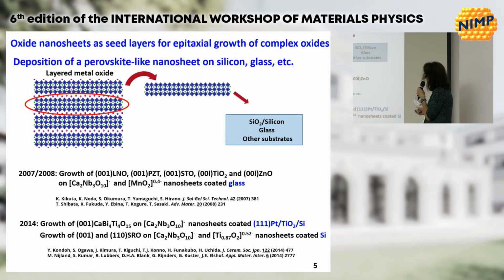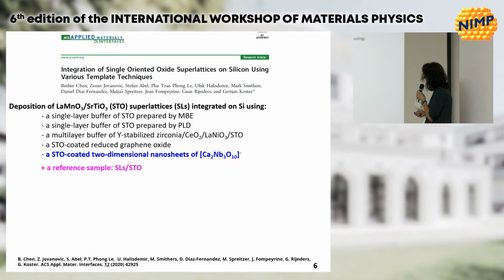It was shown for the first time in 2007-2008, by two groups in Japan, and they have shown that it was possible to obtain a preferential orientation of different oxides. We have the list here, on nanosheet-coated glass. Then in 2014, it was also shown that other kinds of oxide can also be obtained on nanosheets, on platinum, or on silicon.